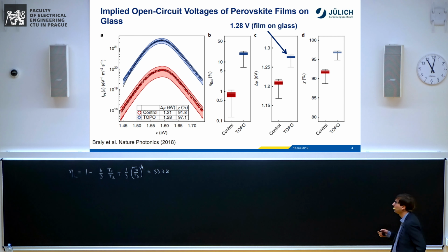Okay, and then also roughly 1 year ago, there was this paper by the group from Seattle, David Ginger's group and Hugh Hillhouse's group, on determining the so-called implied open circuit voltage, not of a solar cell, but of a passivated perovskite film. That means they didn't have charge extracting contacts applied to the film, but they did have passivating layers, and then measured the luminescence of these films.